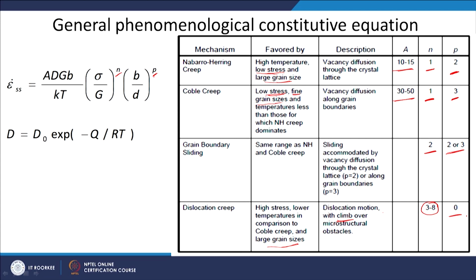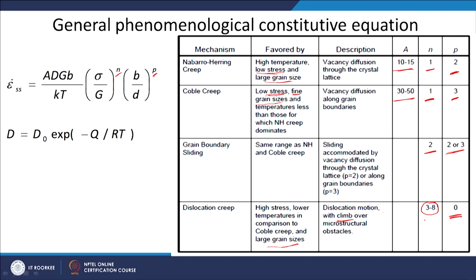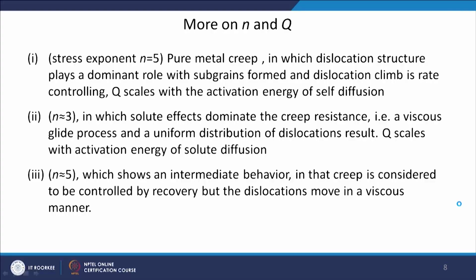There is no grain size dependence. That is why, as you remember, when I was discussing dislocation creep, there was no term for grain size, because it does not depend on the grain size. On stress it has a very strong dependence, and at the same time it has a big range. So depending upon what type of deformation mechanism is taking place, your n will change. More on n and Q, just to clarify this more, because you will keep calculating these whenever you are developing a constitutive equation.